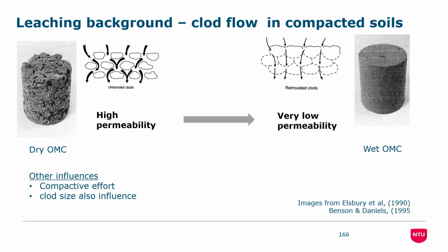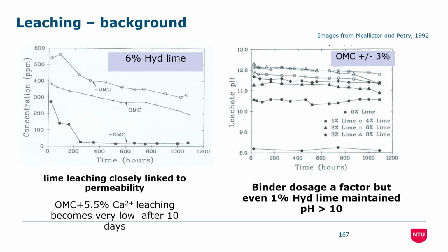So this is now a bit of the background, a theory of how water would flow through soil. On the left side here, we've got an example of a very dry material. If compacted dry of optimum moisture content, you're going to end up with a clod flow based process where water will flow with quite high permeability around the individual clods of your treated material. Whereas if you have a wet of optimum moisture content material that is well conditioned and then compacted, you're going to have a pathway where the water has to go through the whole mass, and therefore the permeability becomes much less, and the likelihood of anything leaching through that is also less.